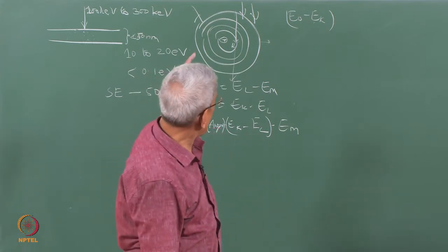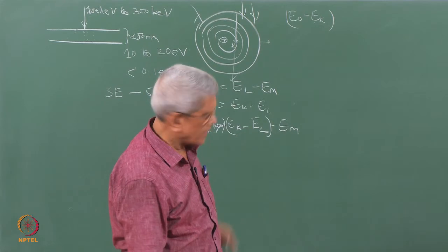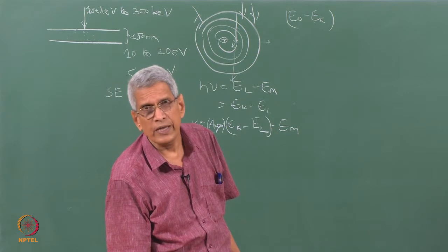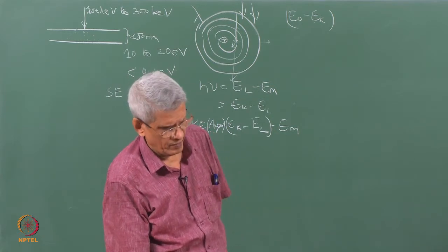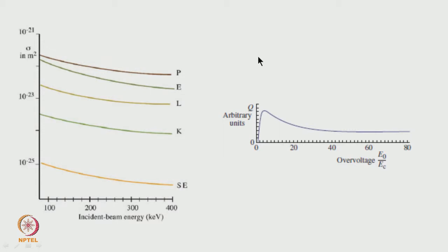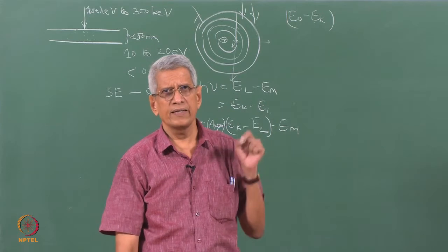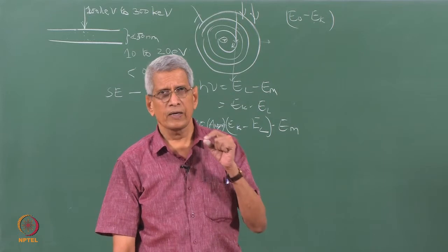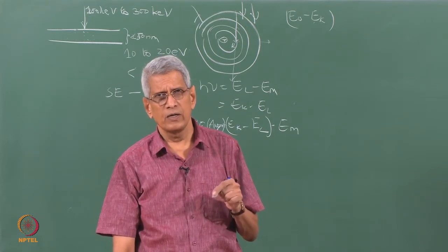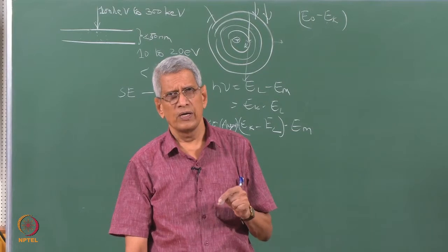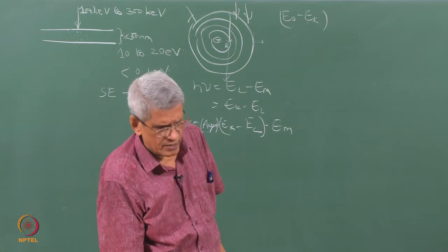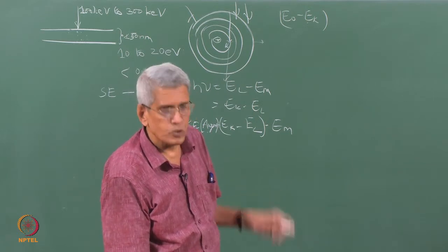If we measure the kinetic energy of these electrons, this can be used to identify the elements present on the sample surface. That means the primary energy has undergone some energy loss, and this energy loss is used to find the composition as well as to do a quantitative analysis of the concentration of elements on the sample surface. So, this is called Auger electron spectroscopy.